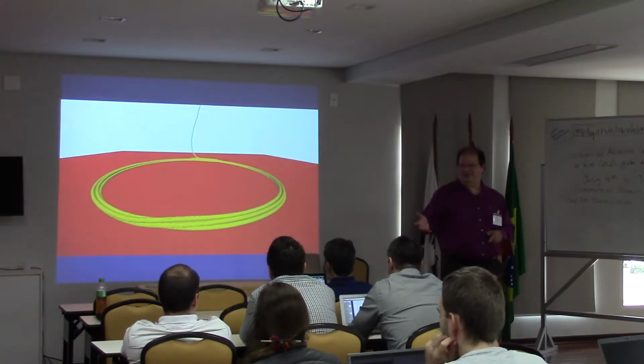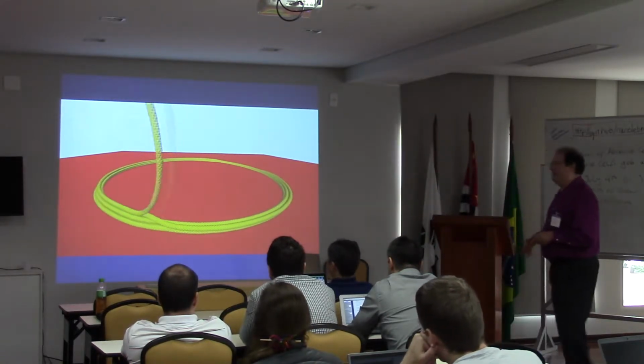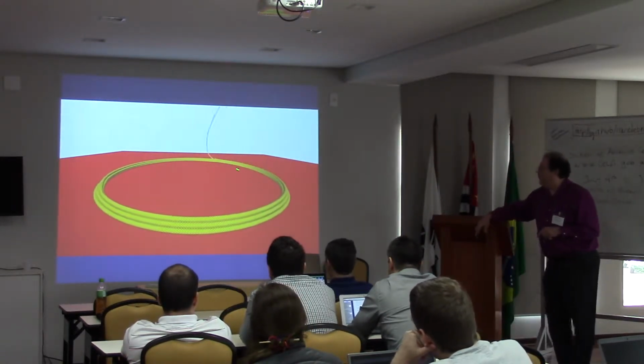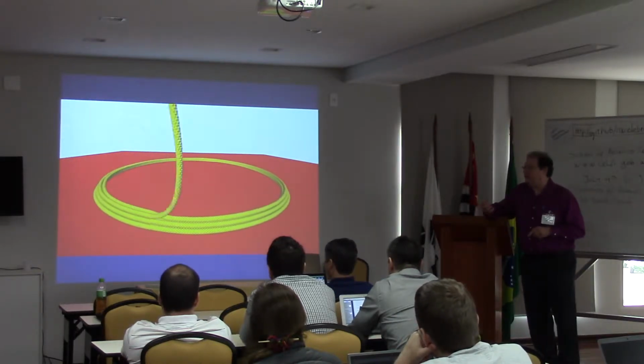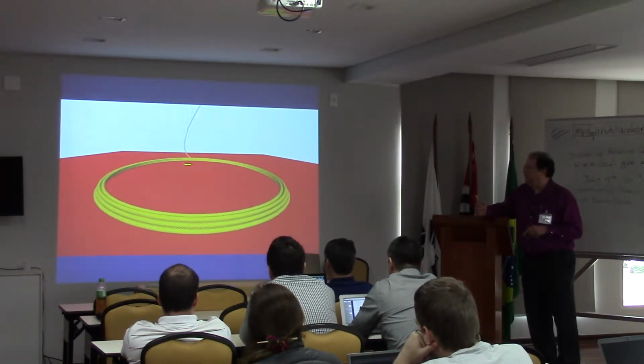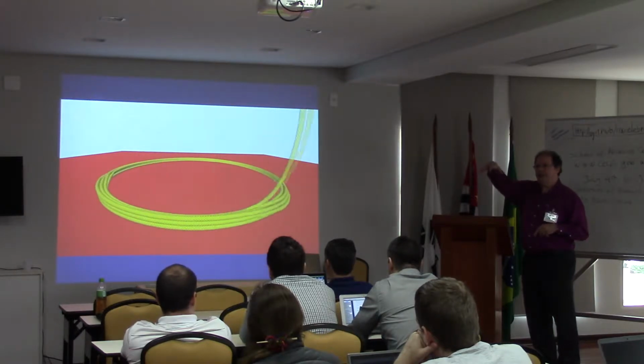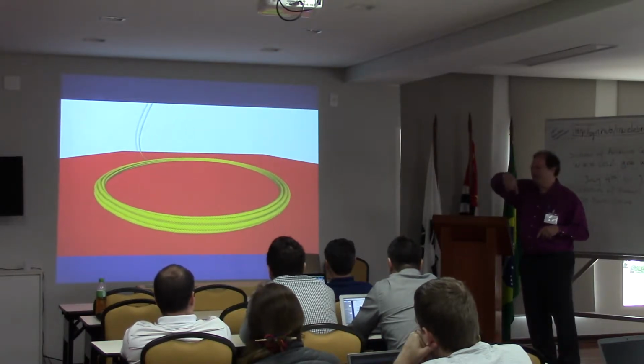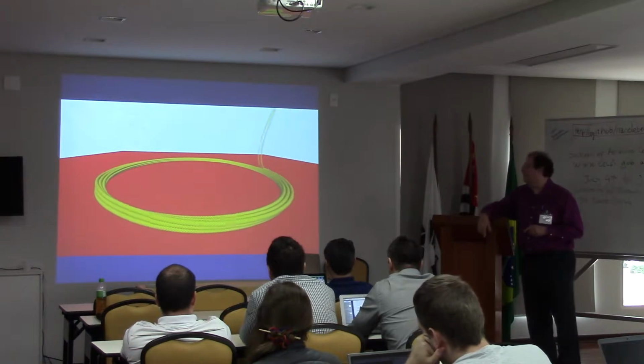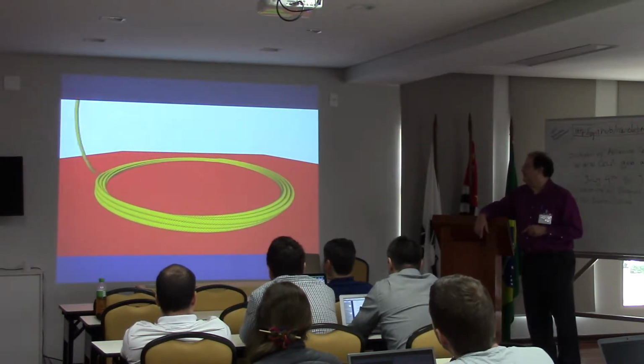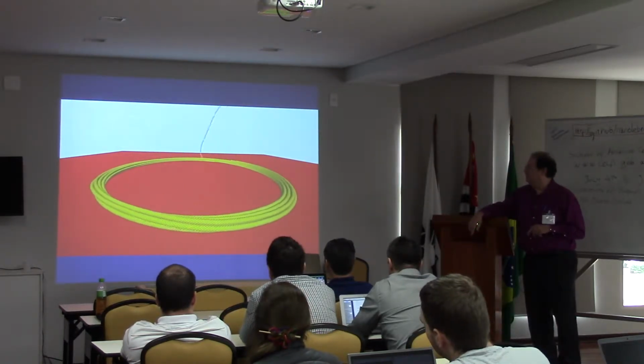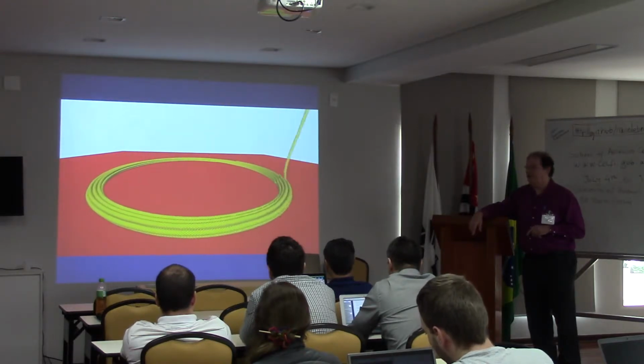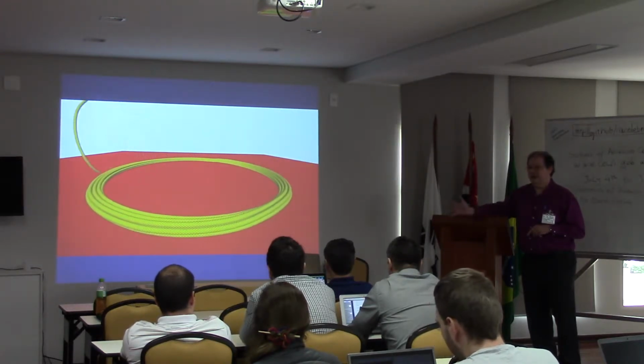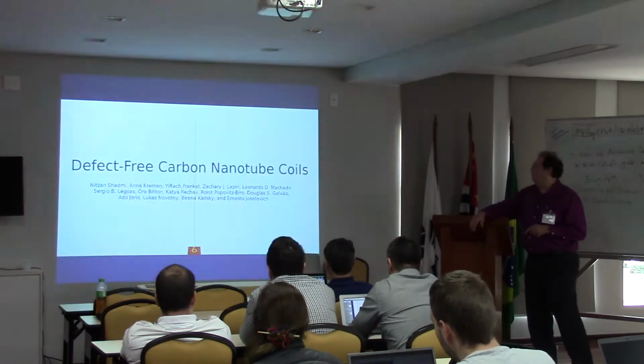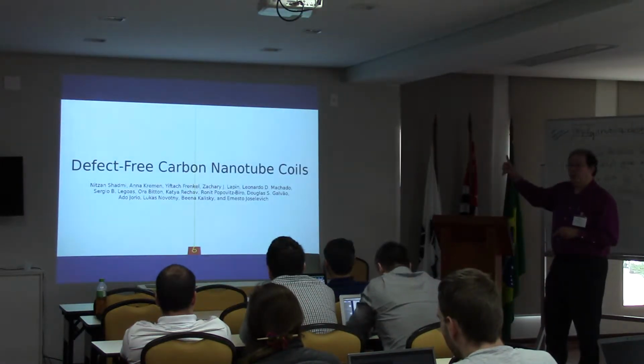It's very impressive. The van der Waals interaction is so strong that it helped the coil formation. It dropped on itself and started self-organizing the structure. There is some thermal vibration, but see, it's very resilient. It survives the thermal effect. And the simulation is very long, 1 micron long. We're talking about a very, very large simulation.